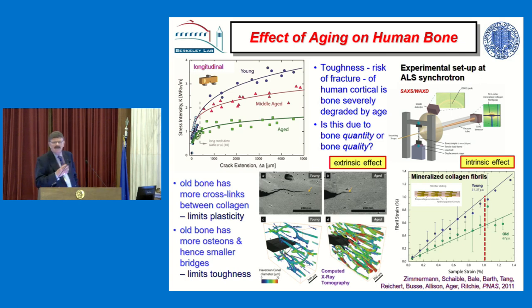And they are these uncracked ligaments, the bridges of the crack. And it turns out that as you get older, the number of osteons that develop in your bone increases. Remember, the boundaries of the osteons are where the cracks deflect. So these little uncracked regions are much larger in young bone, because the osteons are further apart. But when you get to older bone, that bridging mechanism is diminished because you have too many osteons.